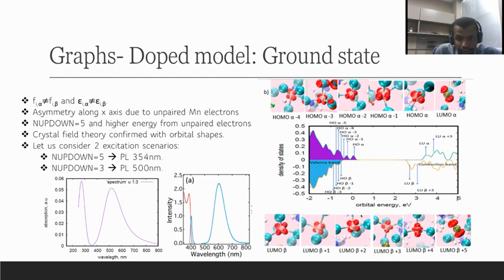And so if we look at the orbitals as well, we can see that the orbitals from HOMO alpha -4 to HOMO alpha look like the d orbitals from manganese that I showed in the earlier two or three slides, and that the LUMO from LUMO beta to LUMO beta +4 as well are the ones from the manganese atom or ion. But then after that, as we go a little bit further, we can see that the LUMO beta +5 is the one on lead, the 6p orbitals from lead.